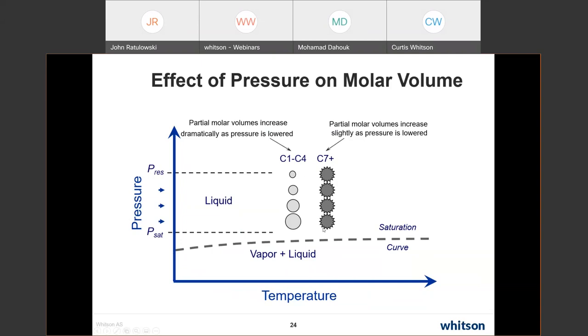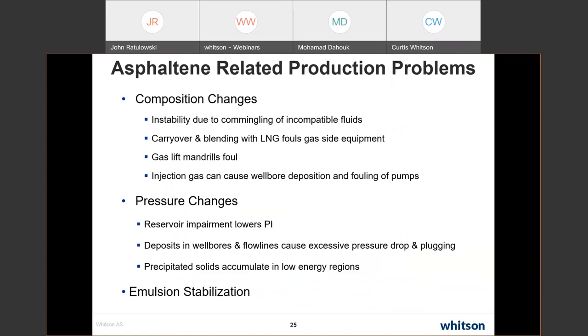So when I get down to the lower pressures, on a volume basis the asphaltene sees around it much more saturate than aromatic liquid. So as a consequence, it can be destabilized. And of course, if you run this through thermodynamic packages, you can just look at the chemical potential changes and you can see this happening. But from a physical standpoint, this was a little easier for me to understand, particularly when I was working on this early in my career.